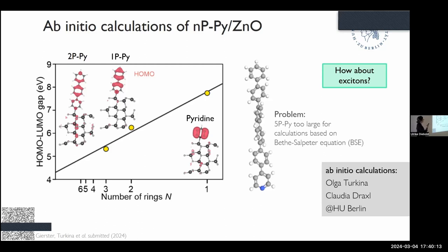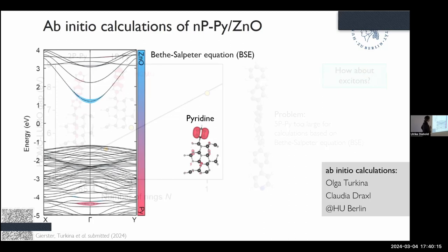With this trick, we were able to simulate the situation using BSE. So when you calculate the band structure and the excitonic features using BSE for the pyridine zinc oxide system, you find that there are hybrid excitons. The HOMO sits here in the valence band continuum of the zinc oxide, and the electron sits in the conduction band. But this is, of course, not the situation that we have in our experiment.